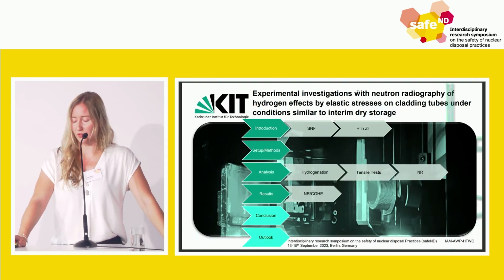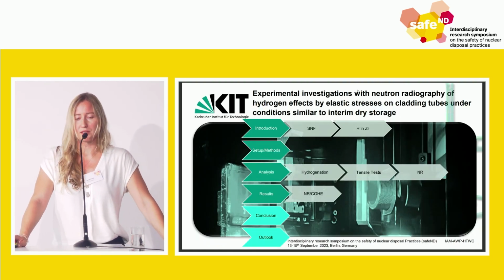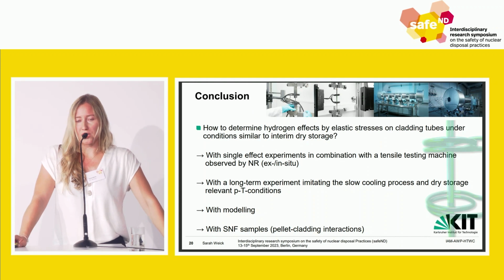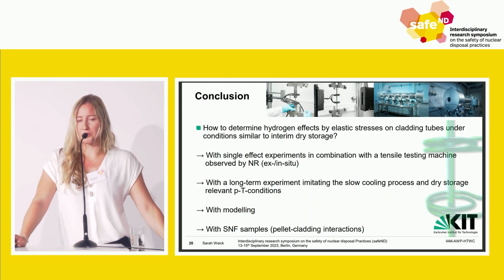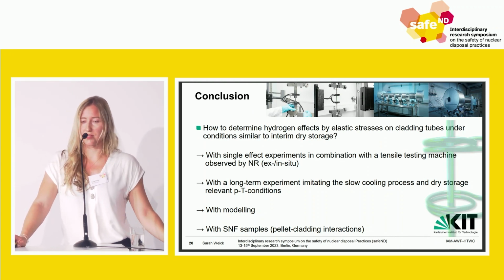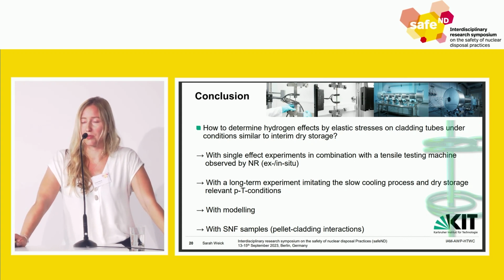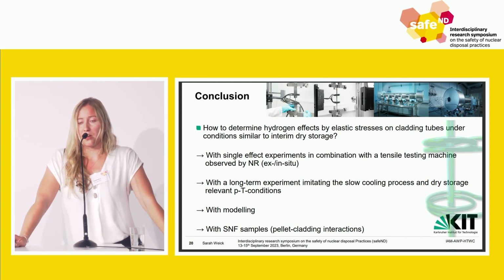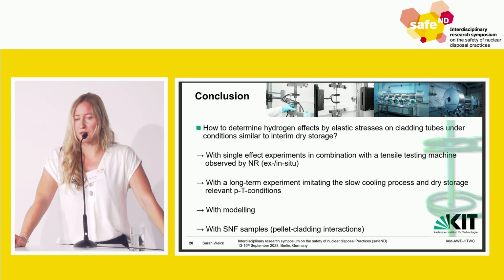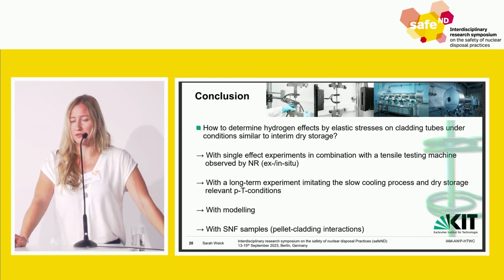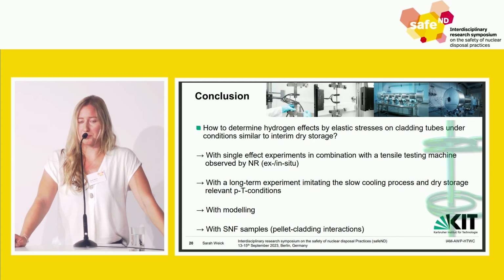But we still try to get new results. So generally, how would you determine hydrogen effects by elastic stresses on cladding tubes under conditions similar to interim dry storage? We do it with single effect experiments in combination with tensile testing machines observed by neutron radiography experiments, both in situ and ex situ.